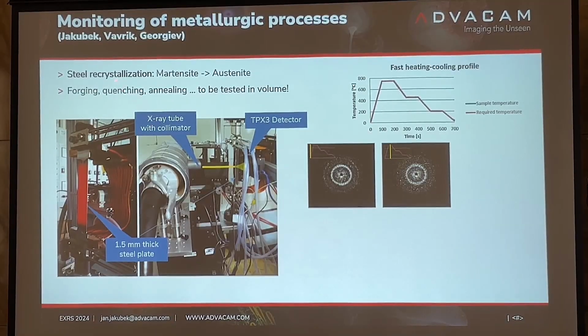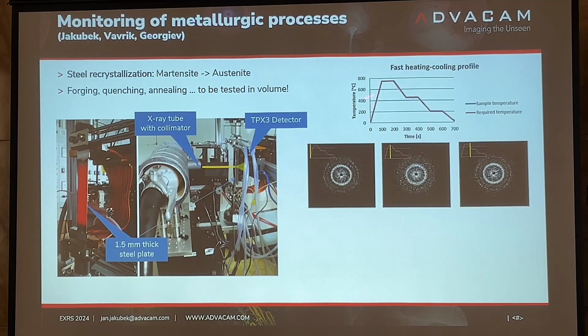We took this plate of steel, we put it into some setup, we heated it up to 750 degrees C, and we wanted to see recrystallization of this steel from martensite to austenite and back during the cooling. So here you see the sample. Here there is the setup. The sample is hidden inside. It was a pretty complicated thing. There is an X-ray tube with collimators. The detector is here behind.